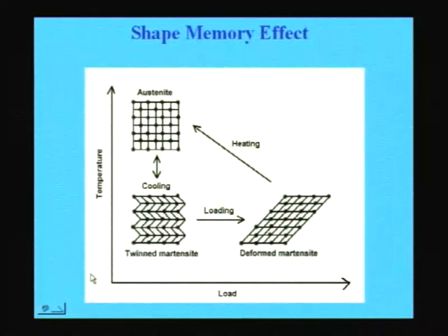And how does this occur? A schematic picture is shown here, where the austenite at high temperature is brought to the martensite by cooling, and during this transformation there is a lot of twinning that takes place inside the martensite. When you deform this at temperatures below the MS temperature, this martensite gets deformed, and if you start heating this deformed martensite, you get back this austenite, and whatever deformation you have given is lost and you get back this original shape, and that is what we call the shape memory effect.